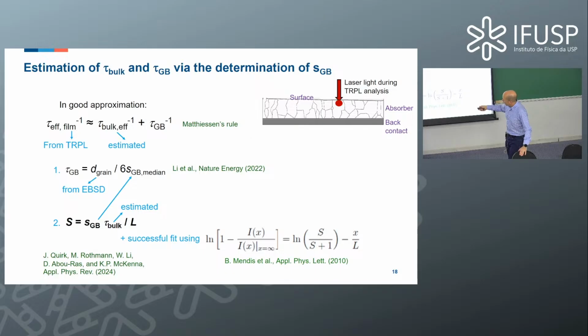And then we put this bulk lifetime here into this equation. So then we have basically this equation, and this is the fit parameter, as I said. And so we have to successfully fit basically the linear function here. And then if we determine the recombination velocities, we have a median of all the values that you saw, yes? This we put in this equation.